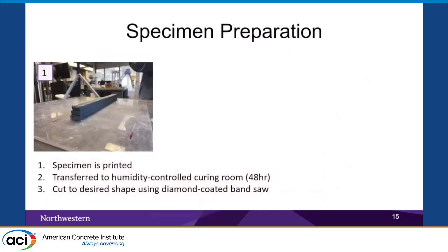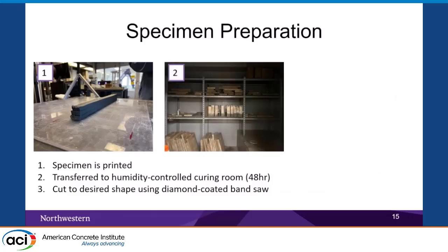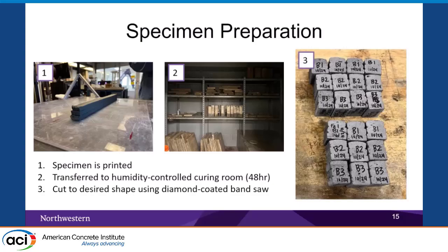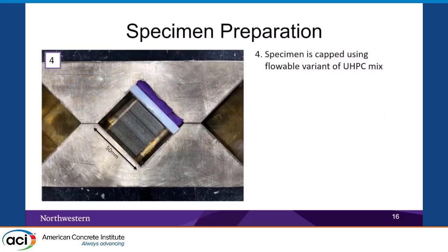So the steps were: print, move to the curing tank, after 48 hours cut samples based on the mechanical test that we're going to do. And here is the preparation of the sample.